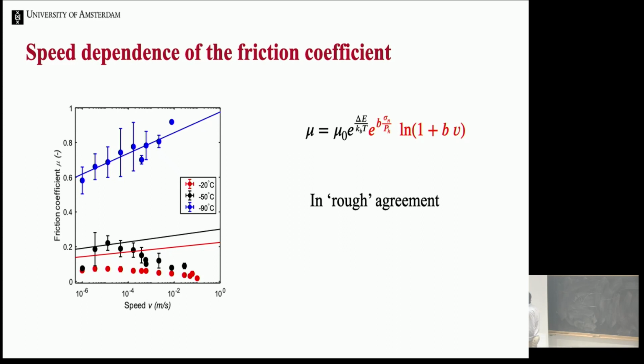But if you take the confinement effect of the counter surface into account, you basically predict that there's a logarithmic dependence on the speed, and that is really well borne out in the data for -90. And it's a bit less good at higher temperatures because especially for rough surfaces we have a lot of plowing there, and so the quantitative comparison is actually a little bit more difficult. So I would say it's in rough agreement.